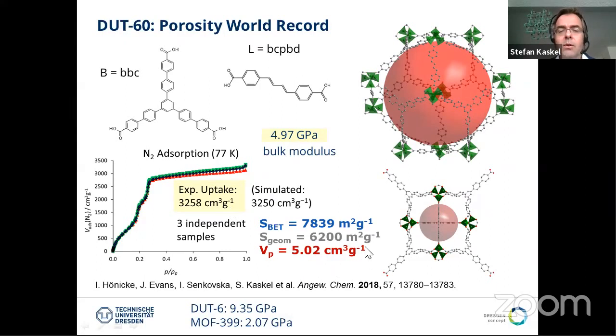And of course, another option to characterize it, which is also very appropriate, is the pore volume. The specific pore volume is 5 cubic centimeters per gram. This is almost one order of magnitude higher as compared to a zeolite, which has typically about 0.5 cubic centimeters per gram. And of course, these ultra-high porosities. So we proposed to talk about ultra-high porosity above 5,000 square meters per gram, which is an arbitrary value.